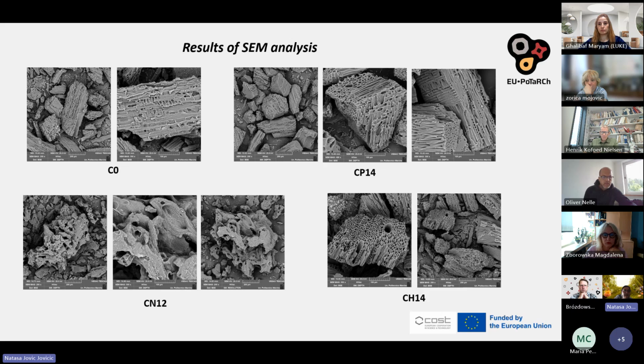The sample activated by sodium hydroxide exhibits a rough, irregular, heterogeneous surface with visible fractures, and the sample activated with hydrogen peroxide has a perforated and cracked macrostructure, showing large open features and cylindrical channels at the surface. Some regions resemble vascular-like plant structures typical of biomass-derived char.